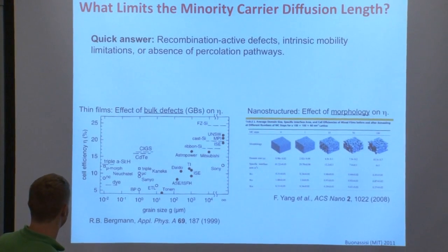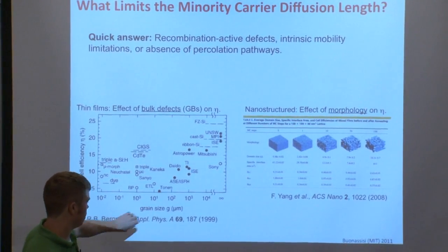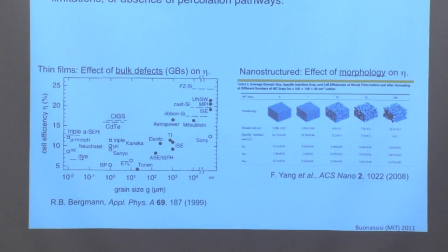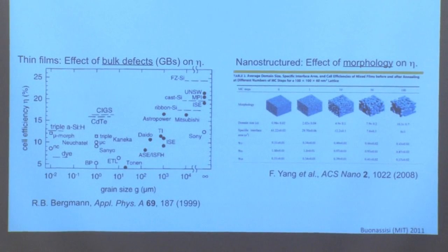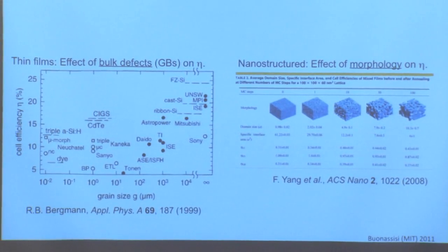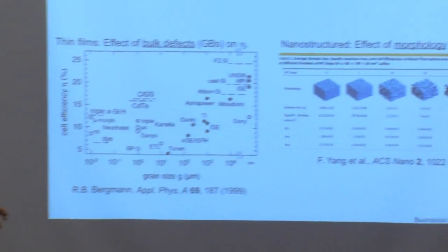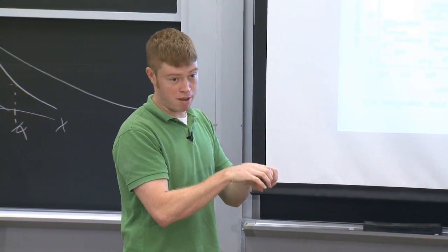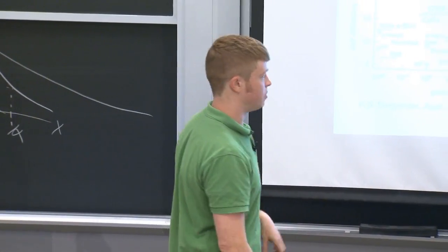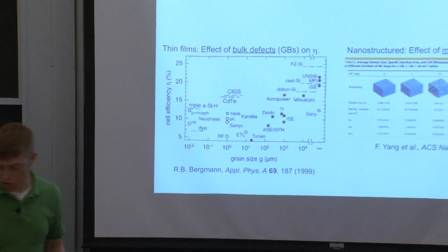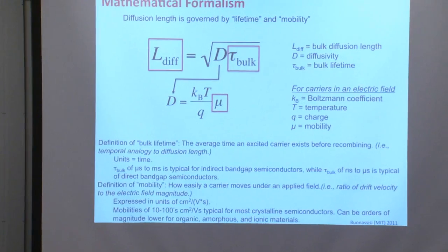And a lot of this is actually determined by the size of grains in your material. On the cell that Tonio brought in earlier, sorry, I don't have a good example, it didn't just look like one flat plane. You could see different grain orientations. The edges of those grains are called grain boundaries, and those can act as recombination centers and actually reduce what's called your lifetime, which we're going to get to on this slide.